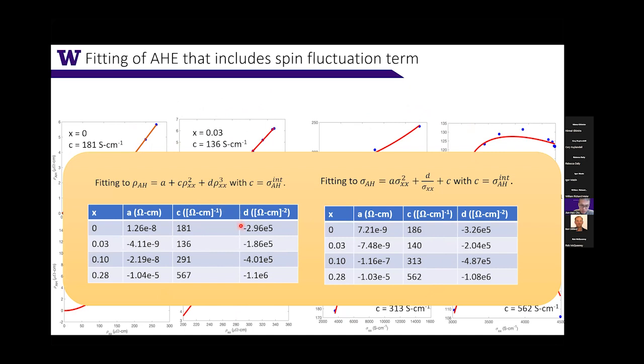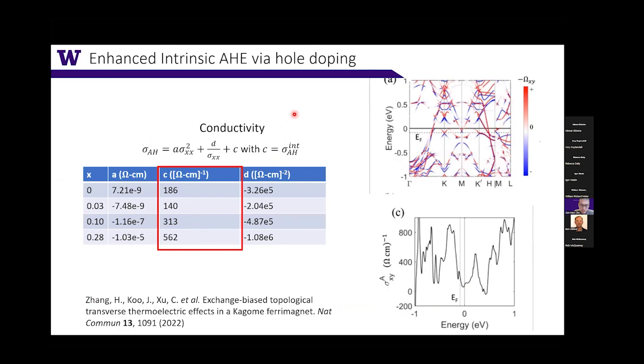But the coefficients you extract more or less agree with each other. And perhaps more importantly, the intrinsic part shows very consistent results: as you go from the parent compound to the doped compound, the intrinsic anomalous Hall conductivity progressively increases to a much larger value. So if we look at some calculations, here I'm pointing to an experimental work where Binghai Yan did calculations on the doping dependence of the anomalous Hall conductivity. And I think Igor's and Nermel's paper also has something similar.